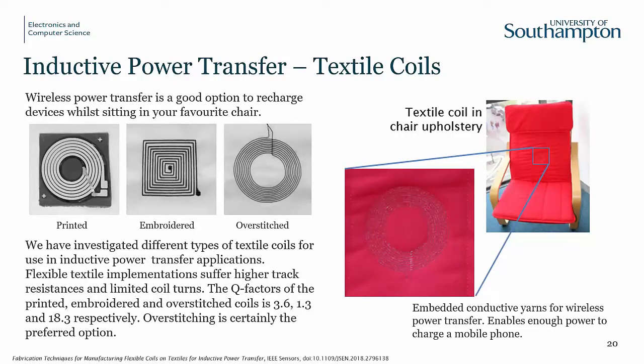If you operate the system, so you have two coils, a transmitter and a receiver, at resonance at a particular frequency, you can extend the range and the efficiency of the transfer. So we've looked at textile coils and how well they can be used in this resonant mode to increase the power efficiency and the amount of energy you can transfer. So we looked at printed coils, embroidered coils taking a sort of silver-coated yarn, and then we looked at overstitching.